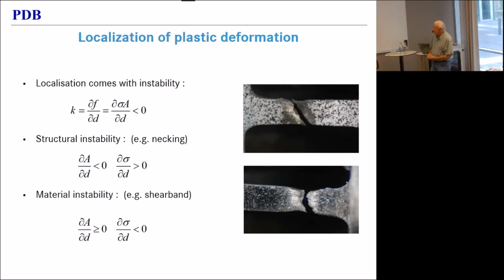So there's two different kinds, right? Because the force is equal to the true stress times the cross-section. You can either have an increasing true stress with displacement and a decreasing cross-section. That's what we call a structural instability. Or you can have the reverse. You can have an increasing or a constant cross-section with a decreasing true stress, which is a softening, and that would be a material instability. An example of the first is necking. An example of the second is a shear band.